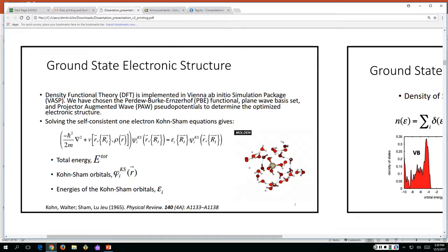But also because the spin orbit coupling takes into account the alpha and beta spin mixing into its orbitals, it's going to have some component of beta taken into account. Meaning that if we would look at the density of states for the spin orbit coupling, I would also expect to see some type of unoccupied band just above the valence band that would correspond to about the same absorption energy. Right, because when we have this wave function for the spin orbit coupling, it's comprised of two components, up and down. Does that make sense?